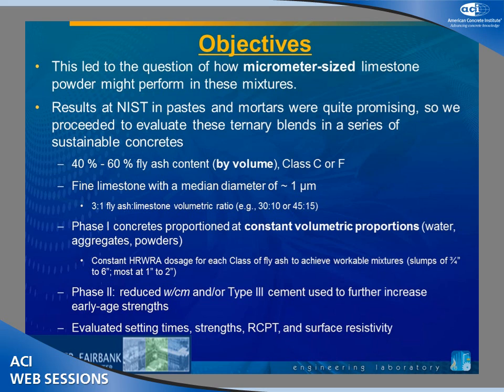The F-ash, on the other hand, is a very well-behaving F-ash, very pozzolanic, only has about 1% calcium oxide. So we wanted to contrast the behavior of those two. We had looked at different finenesses of limestone. For this study, we selected one with a median diameter of about 1 micron. There's another product that's about double that would perform fairly similar to this one.